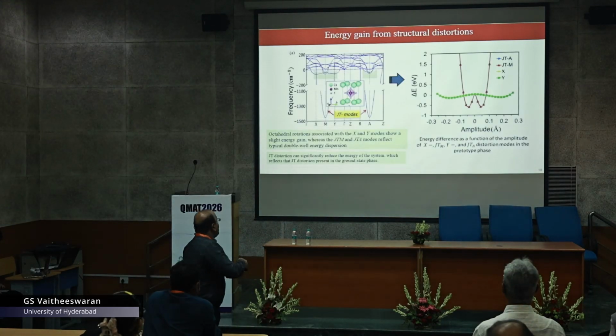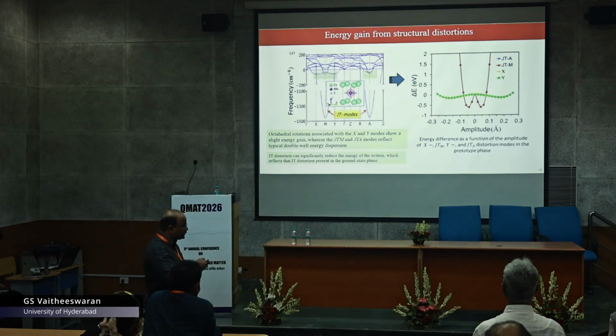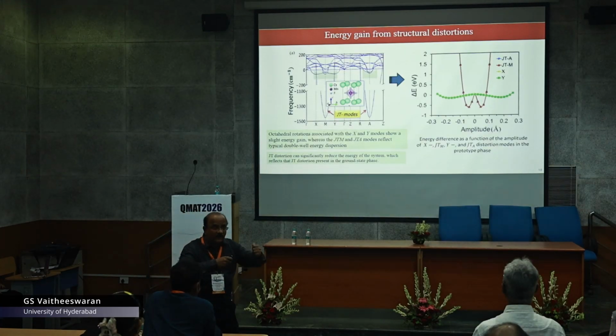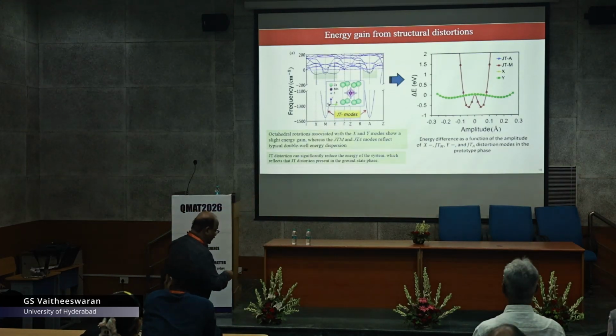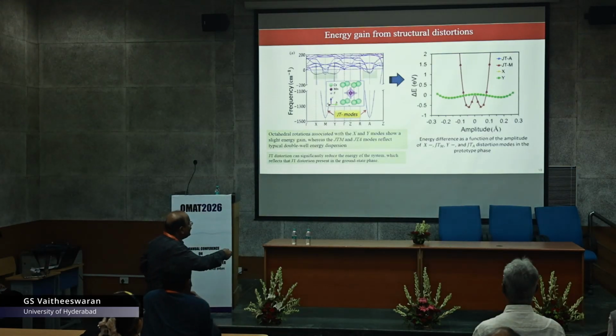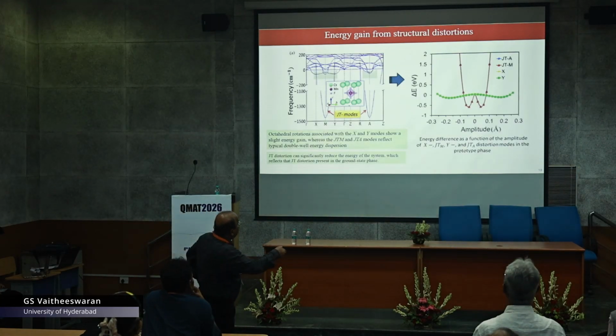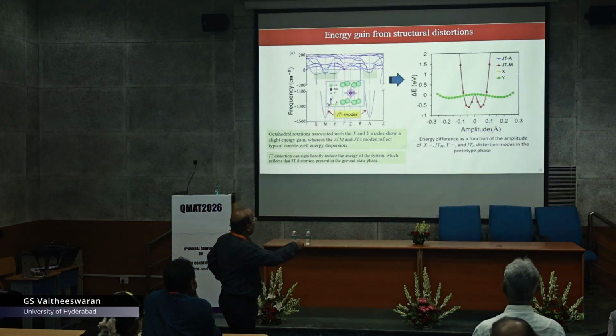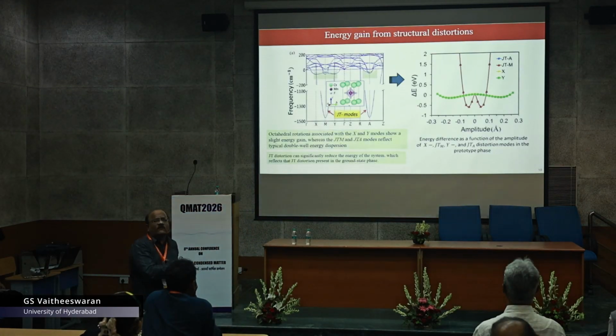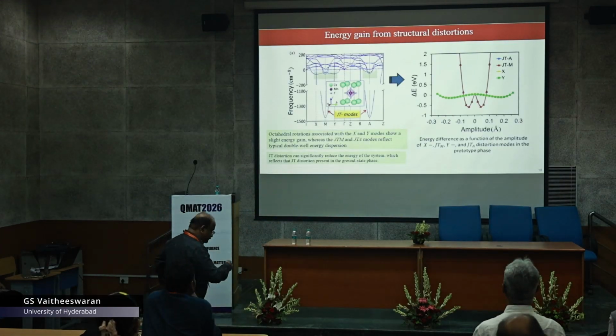And this is the energy gain from the structural distortion. We tried to move the atoms, compute the energy and plot this. These modes, as I suggested, are Jahn-Teller active, and we do get a double well like feature when we do this for A and M, whereas for X and Y it is not very significant or prominent.